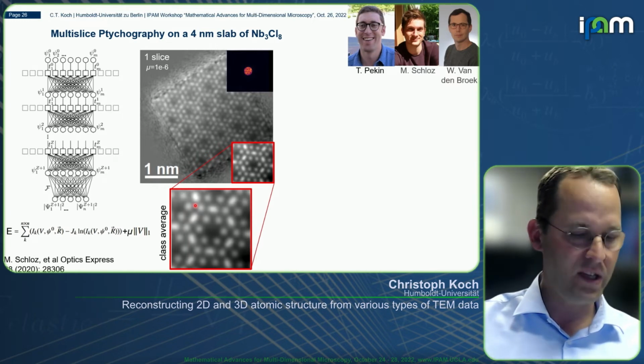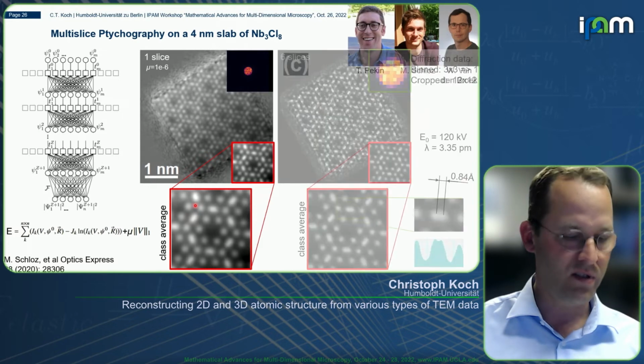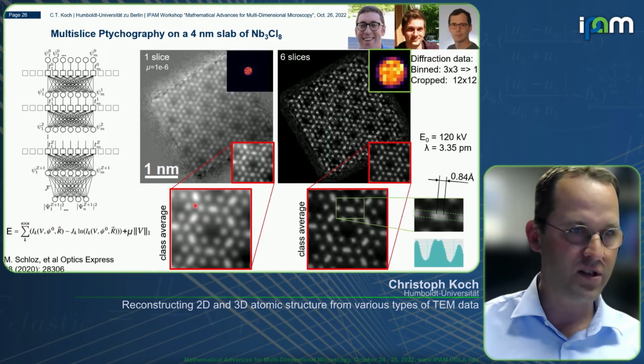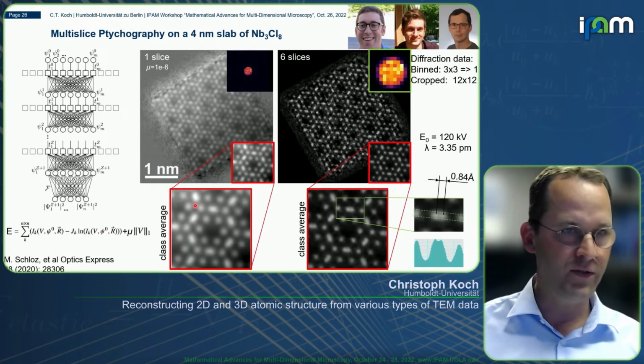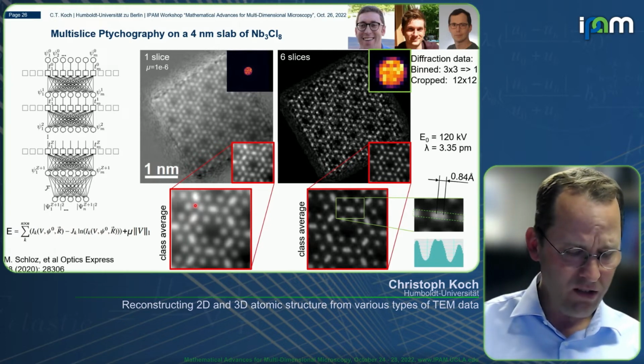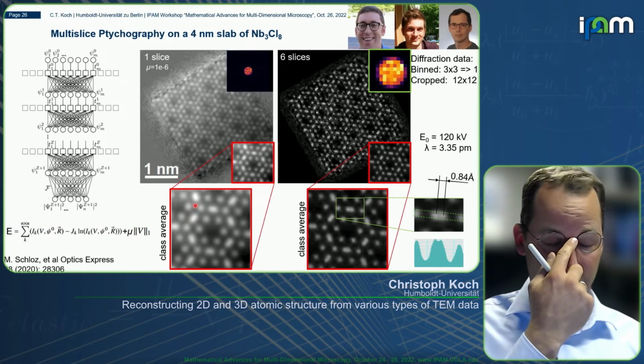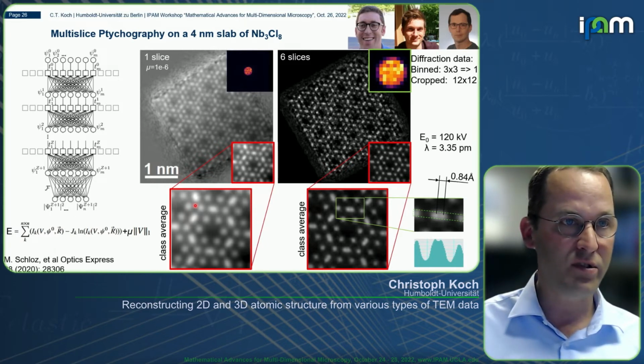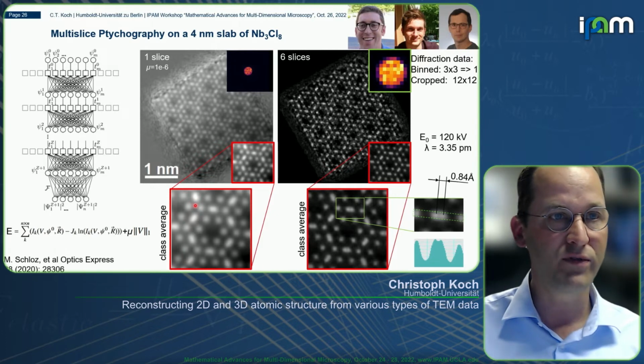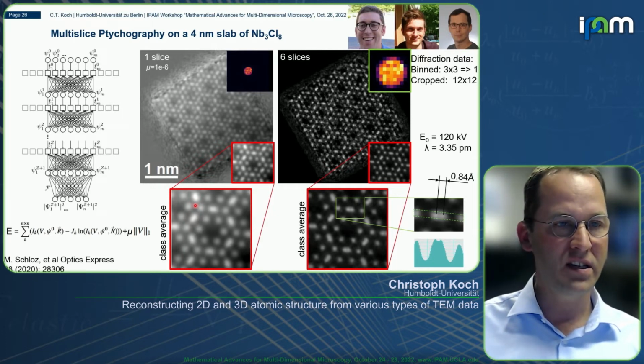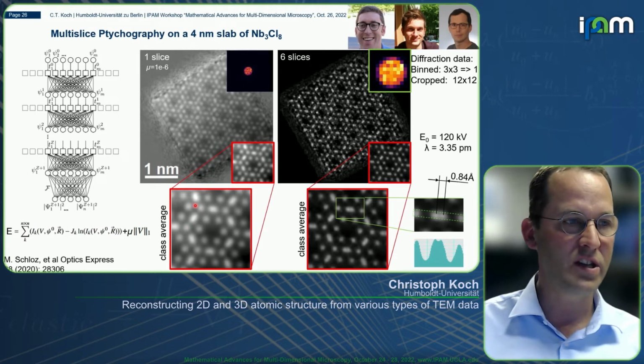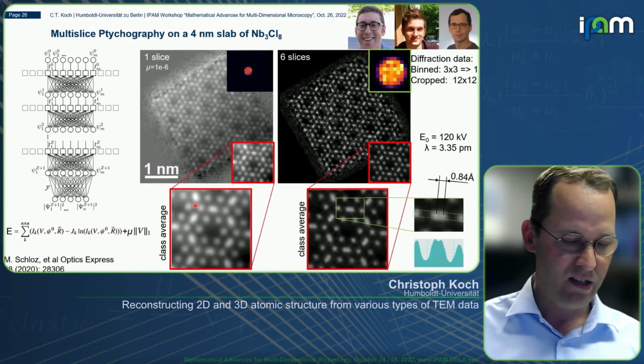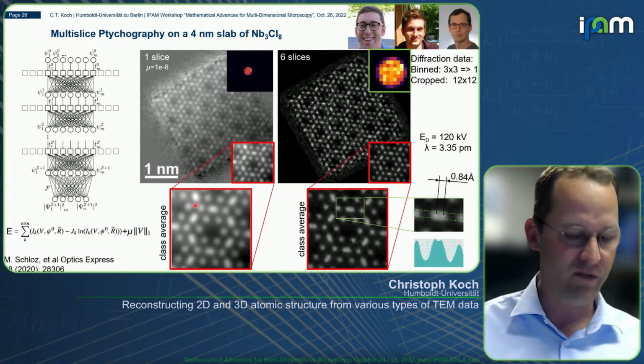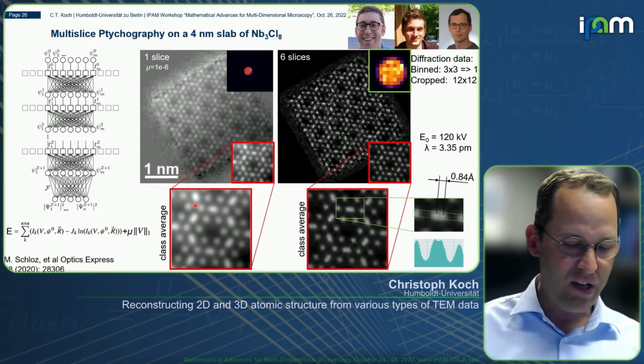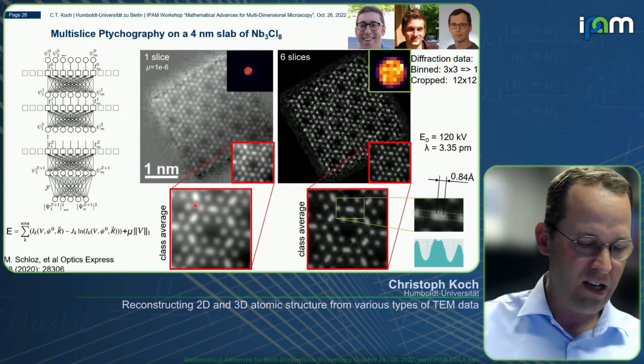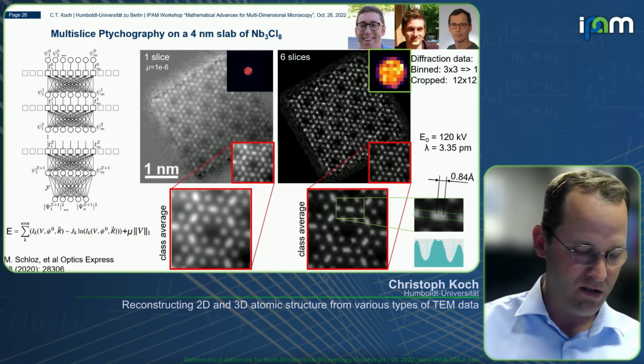But if we include multiple scattering, and Dave Muller and Zhen Chen and his group have shown this in multiple presentations, you not only get a three-dimensional reconstruction of your sample, but your lateral resolution also improves, because the multiple scattering is more faithfully treated. So you get a much better agreement between your forward calculations from the current estimate of your model and the experimental data. But in this paper, in addition to applying 6 slices